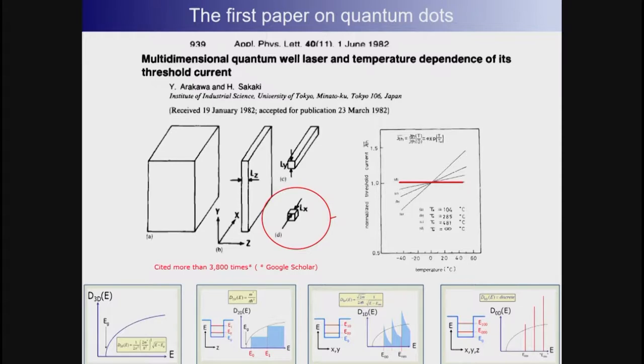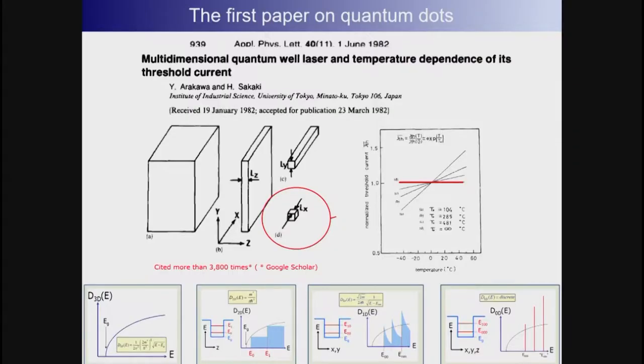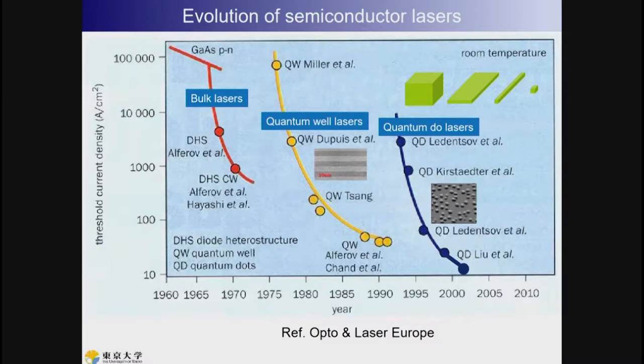The main reason we can get very stable operation of the threshold current with respect to temperature change is that the three-dimensional confinement realizes completely discrete energy levels, which results in a delta-function-like density of states. As a result, electrons are always confined in the ground state and are not disturbed by the increase of temperature. This is the main reason for the temperature stability of the threshold current. Also, the small volume effect is very important.